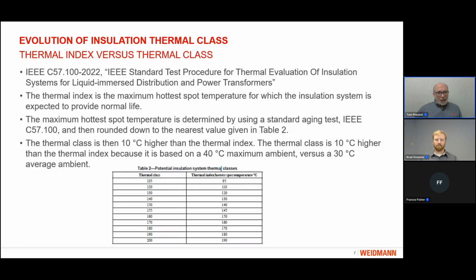So if you look at thermal class here in Table 2, a thermal class of 120 equals a thermal index of 110. So if in the test, any result between 95 and 110, it would then be rounded down to the next value. So if, for example, the test came out with a thermal index of 115, it would be rounded down to 110, and then the thermal class is 10 degrees C higher than the thermal index.